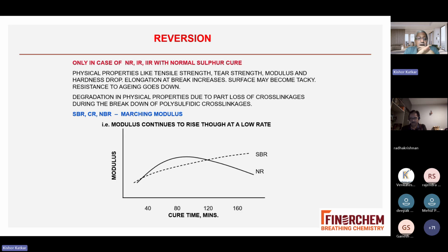You can see here the vulcanization curve, modulus against cure time. In the case of natural rubber, once you get the optimum cure, if you continue the vulcanization, you will get reversion. Your modulus is coming down. Obviously, the performance will come down. In the reverse case, with synthetic rubbers like SBR, polychloroprene, nitrile, what you observe is marching modulus. What is marching modulus? The modulus will continuously go up, even after vulcanization, even during service.